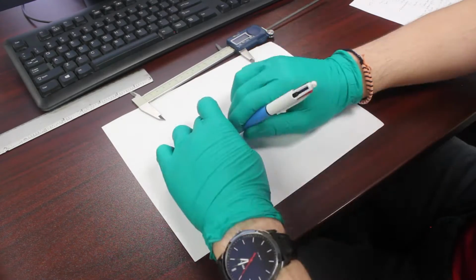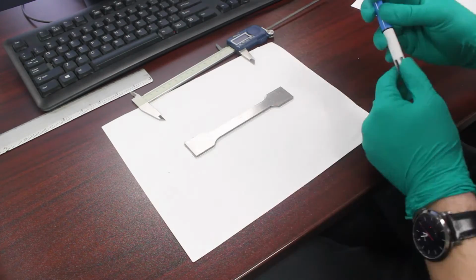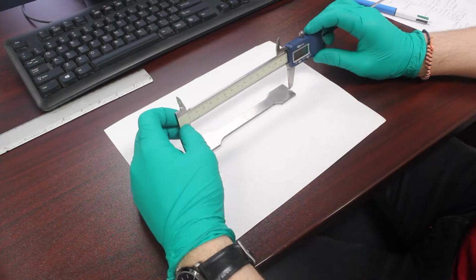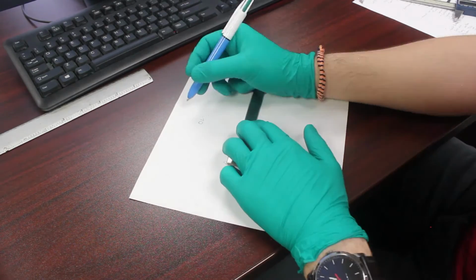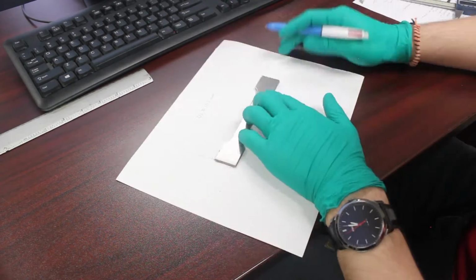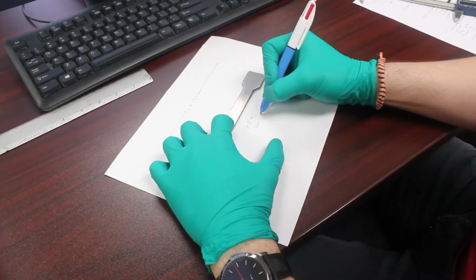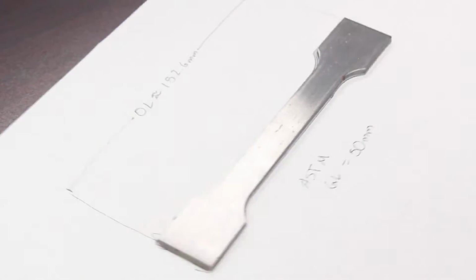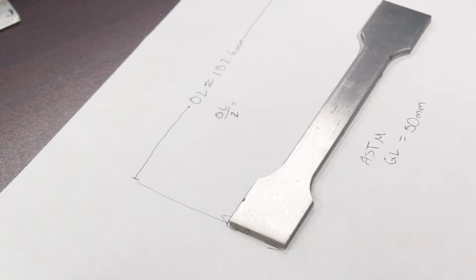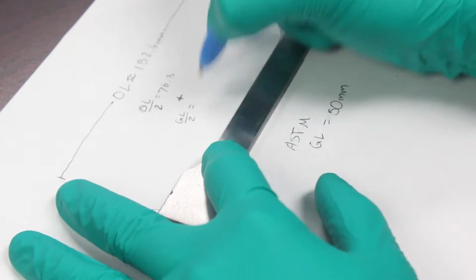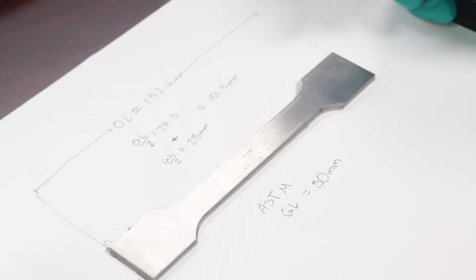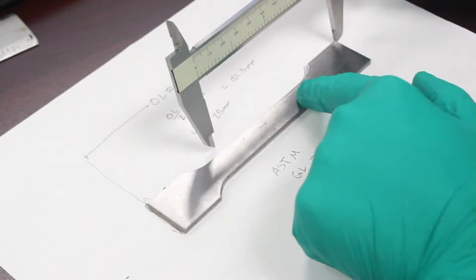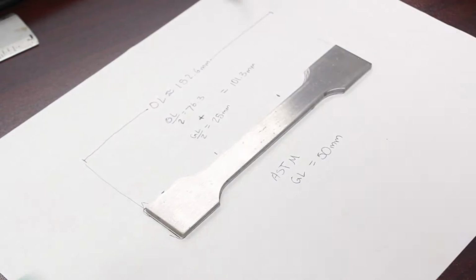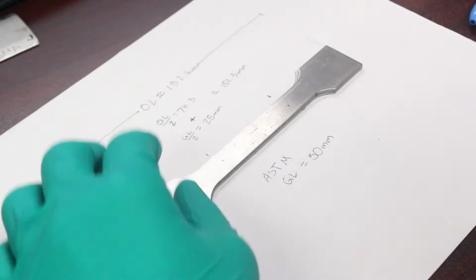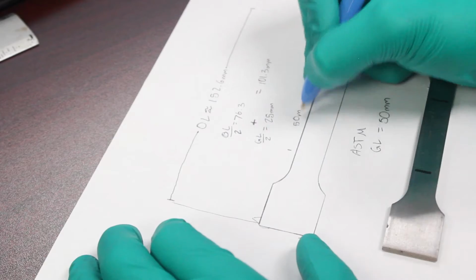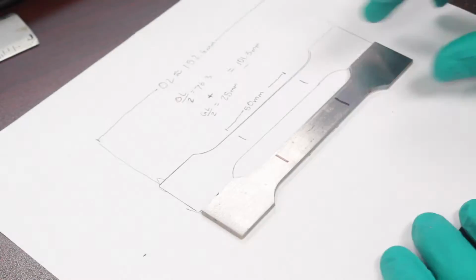Next, we're going to measure and mark the attachment points for the extensometer. Here, your TA Diego is showing a great way to keep track of all your work when doing this. First, measure your sample, the entire length, and divide that in half. The gauge length will be 50 millimeters, so add half of that, 25 millimeters, to half of your overall length, and you will find about 101.3 millimeters for this sample. Measure from one end to the other using that length and mark on those positions so that you have a 50 millimeter gauge length marked in the exact center of your sample.